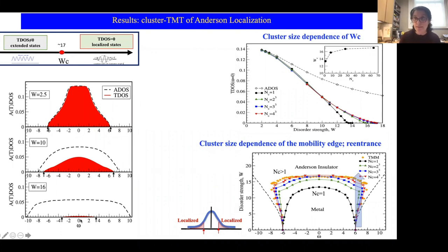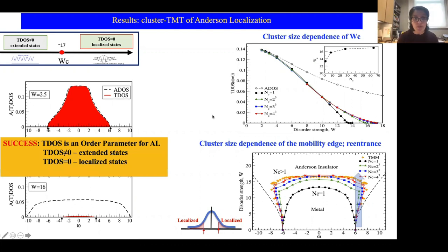So one can do this analysis for different cluster sizes, right? As shown here on the top right, and extract the critical value of disorder at which the metal-insulator transition happens. So this is a regime where the typical density of states at the band center has completely vanished, right? So this is a result showing this for different cluster sizes. And you can see in the inset, starting from cluster size 27, we roughly converge to the critical value of disorder strength, about which we don't see many changes. But obviously you can see that this critical disorder strength has strong cluster size effects. So non-local correlations are absolutely important to take into account when studying Anderson localization in this model.